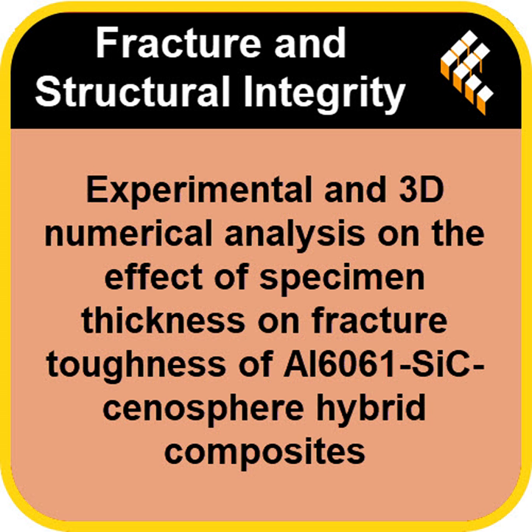Yeah, this is the core result. They found a really definitive trend, and it was the same for all 3 compositions. The measured conditional fracture toughness, K_Q, initially decreased, quite steeply actually, as the B/W ratio, the thickness, increased. Okay, so that proves the thinner samples were giving that artificially high toughness you mentioned, the mixed mode stuff. Exactly. It confirms those thinner samples weren't under full constraint. And then came the plateau, the money shot, as you might say. The plateau is everything. That's absolutely right.